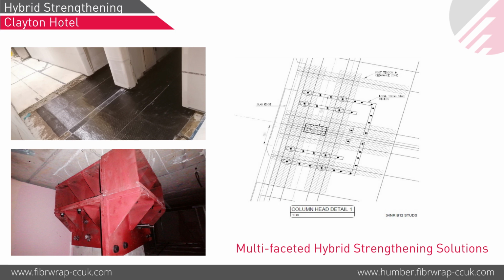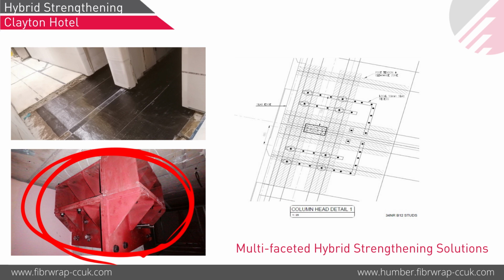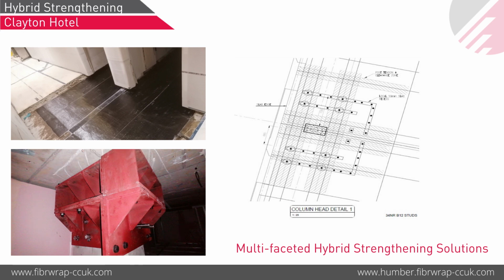So the project engineer, with whom we were already working for beam strengthening and column strengthening, approached us to check whether carbon fiber strengthening would be feasible here. So we said it can be feasible, but in some situations the punching shear failure was at the column perimeter. In that instance, they had to design these steel collars, as we can see in the bottom image on the left hand side, to move that punching shear perimeter away. Then the carbon fiber was applied on top to provide additional tensile reinforcement on top of the slab. So that's how both materials were used for just one type of strengthening there.